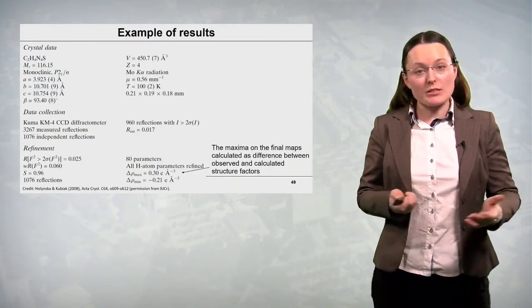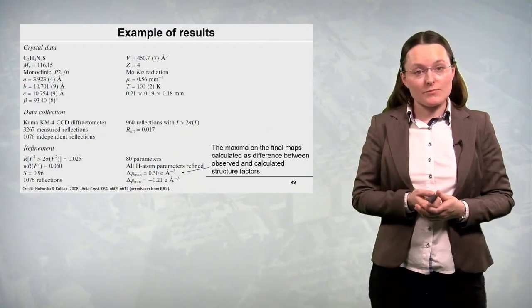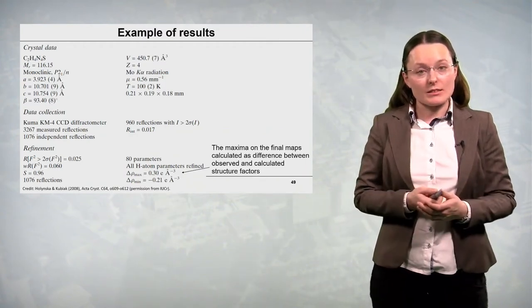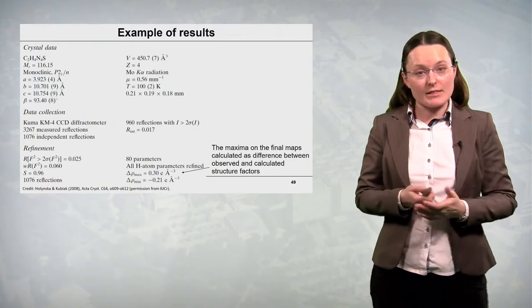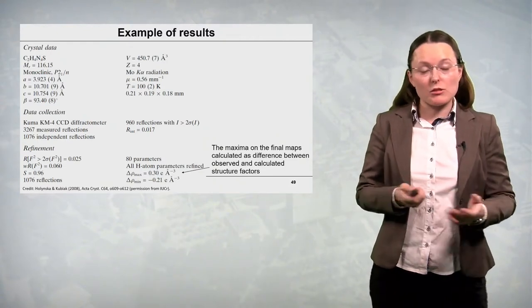and the difference between the observed and calculated structure factors. So the highest maximum in this case should be ideally next to the heaviest atom or in the middle of a chemical bond.